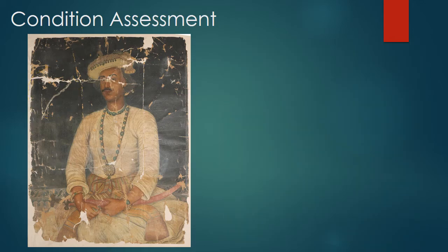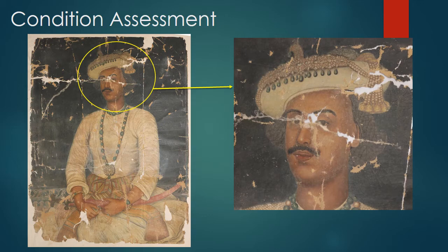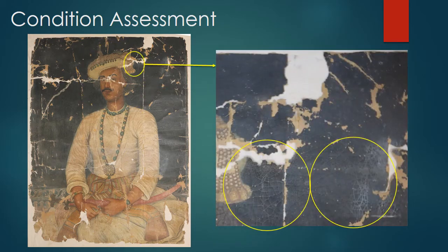In this detailed picture, we can notice residue of termite infestation as well as areas of canvas eaten away by insects. The painting is very old and had a natural varnish coating that had turned yellow with time due to polymerization and oxidation process. Blanching was also noticed. Blanching is caused by trapping of moisture in the varnish layer, causing a change in refractive index or opacity in the otherwise transparent varnish layer. Cracks were also observed in the paint layer.